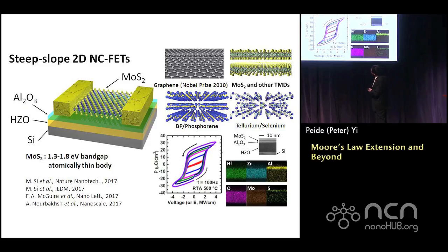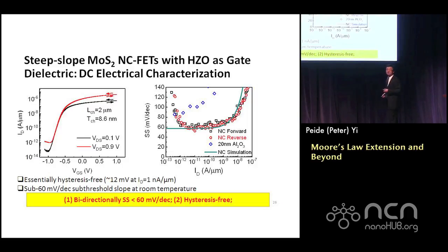So you put this in as the channel, one atomic layer or a few layers. The band gap is 1.3 or 1.8 eV, depending on the number of layers. It's pretty much like silicon. Then we look at the IV characteristics again. It's just current versus voltage here. You can see the transistor can be turned on and turned off without so-called hysteresis. It's almost like a perfect transistor. Of course, what we are very interested in is how fast it can be turned off in this region. This is the key to see if we can break this fundamental limit, the Boltzmann limit, 60 millivolts per decade.